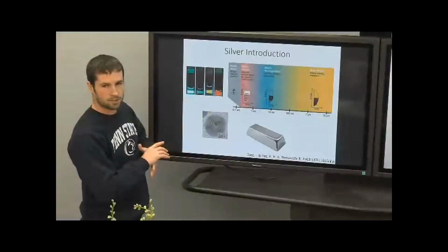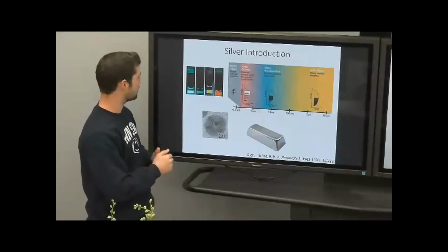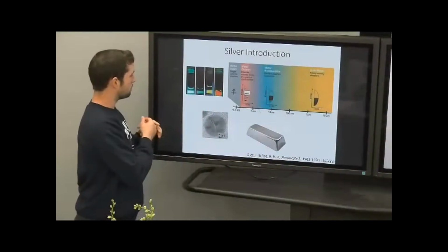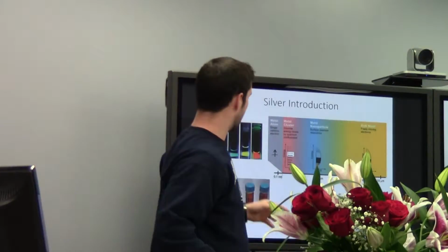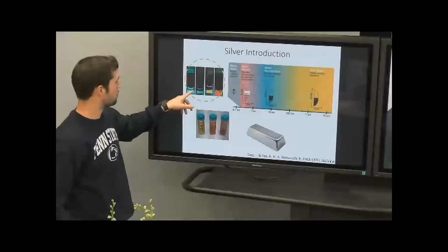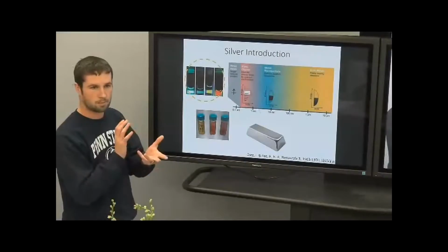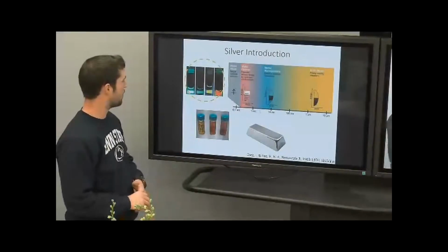Because the density of states becomes discretized for the smaller nanocrystals, that allows for different optical transitions. Work by Diaz and Ross showed that you can actually get fluorescence from these models. And with slightly bigger nanoparticles, you can get surface plasmon resonance, which alters the absorbance properties. In this presentation, though, we'll be focusing mainly on the silver nanoclusters, the very small ones that can be optically active.